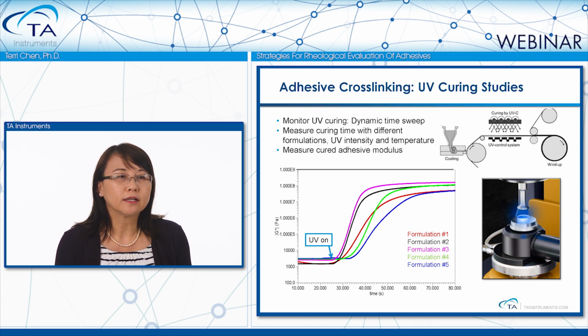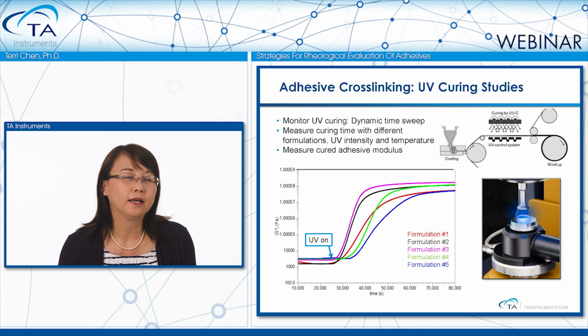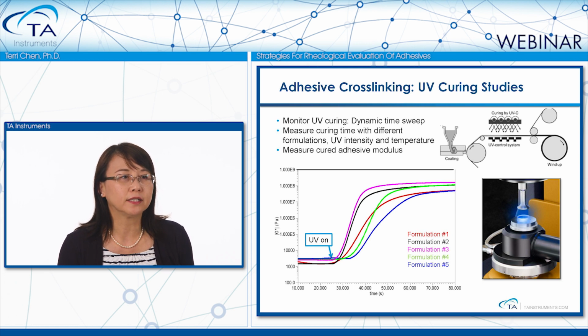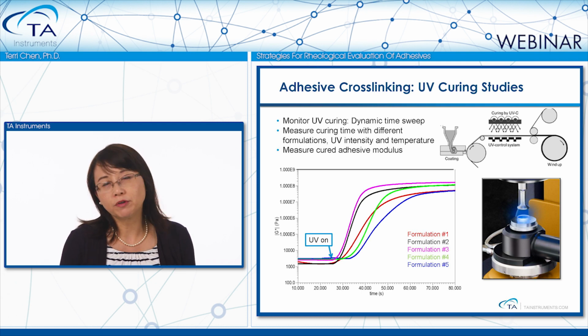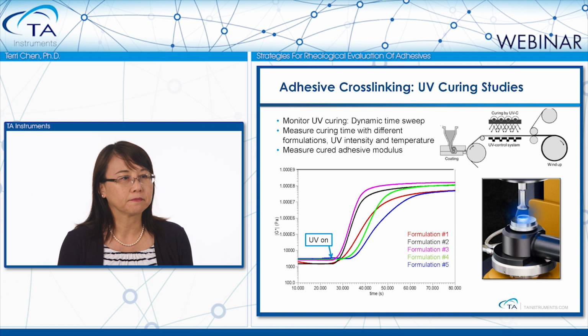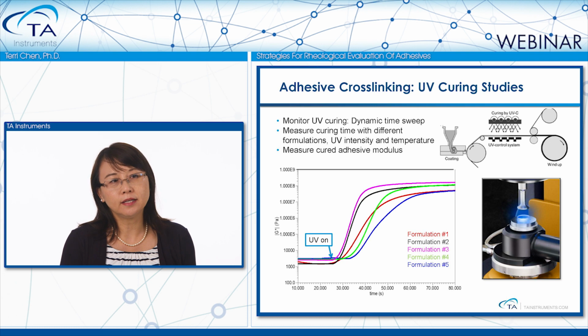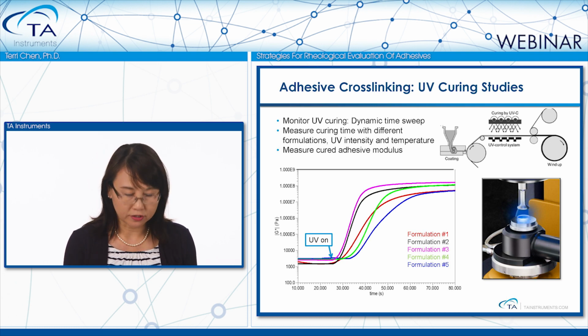The UV light with a controlled intensity was triggered on after 25 seconds of equilibration, and then it remained on for 30 seconds. During this entire time, the modulus change of 5 different formulations was monitored. This type of rheological test allows us to quantitatively measure adhesive curing with different formulations, different controlled UV intensity, and also at different temperatures.